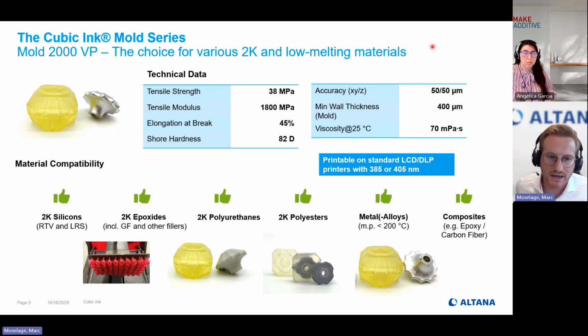Looking at the technical data, generally speaking, these tensile data do not have the importance they have for the object material you use, for example. Summarizing, to have a properly working mold you do need a certain rigidity, you do need a certain hardness, because you print very, very thin walls. And if you have thin walls and the material is too flexible, you're not accurate anymore, and the material will bow like this, and you don't have an accurate result in the end. Apart from this, you do need a certain flexibility.